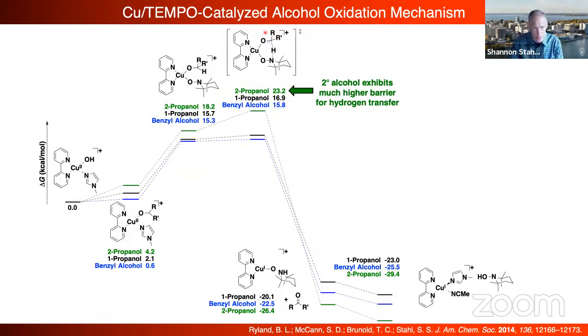So the mechanism involves this 6-member transition state that's shown here. It turns out these are computations that basically justify why, when you have a secondary versus a primary, you can see the barrier to this reaction is higher when you have secondary alcohols versus primary. The other thing that may be worth noting is that the primary barrier in this overall reaction is actually getting the nitroxyl to dock onto copper-2 to generate the cooperative catalyst.